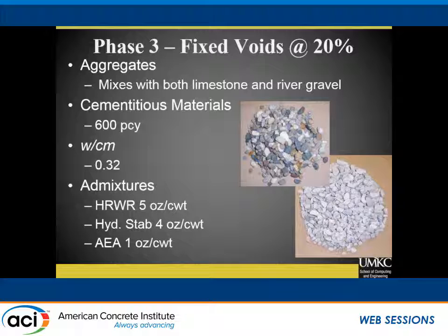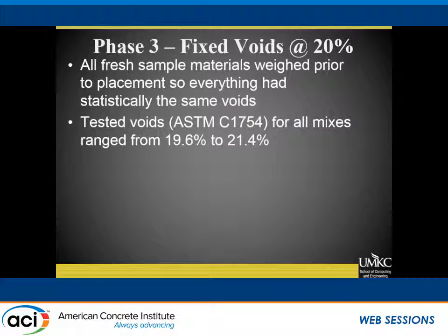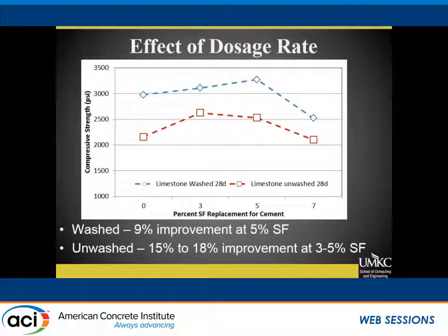So we looked at both limestone and river gravel on this part of the study. So we weighed them out. We did void testing. So our void testing on these, we wanted 20%. It was within the precision of the test. So statistically, they all had exactly the same void content. So effect with dosage rate, so this is limestone, and we looked at versions washed and unwashed. So this is just kind of regular limestone used in Kansas City.